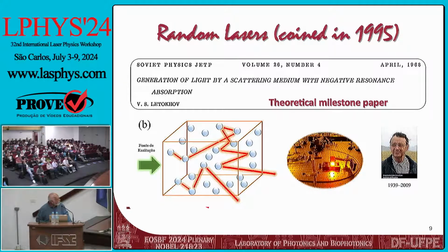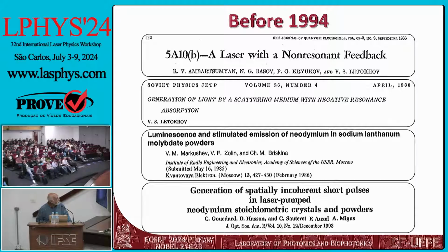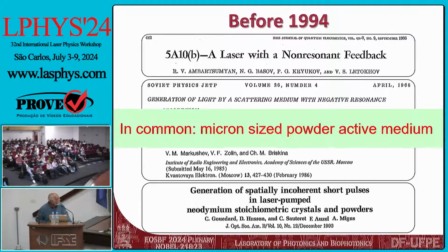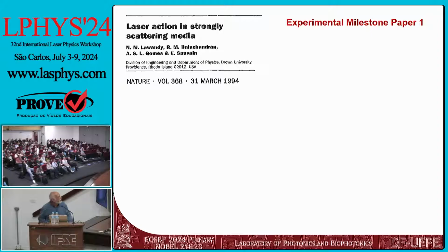is his idea. Between that year and 94, a few papers appeared from Russian groups and a French group exploiting neodymium micropowders mainly, to generate light that they did not claim was laser, but stimulated emission was there. In common, all this work used micron-sized powder, and there would be the possibility, even not being spherical, we could have whispering gallery modes. So the first experimental milestone paper where, in an unambiguous way, we explained and demonstrated laser action in a strongly scattering medium was exactly 30 years ago. So we can say we are celebrating 30 years of that seminal paper.